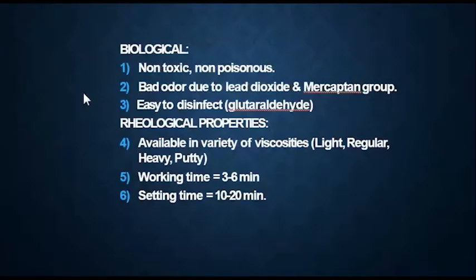Now coming to the properties, it's non-toxic, non-poisonous, but it has a bad odor due to lead dioxide and the terminal or pendant SH group. But it's easy to disinfect using glutaraldehyde. For flow properties, it is available in various viscosities like light, regular, heavy, and putty. It has a working time of 3 to 6 minutes and a setting time of 10 to 20 minutes.